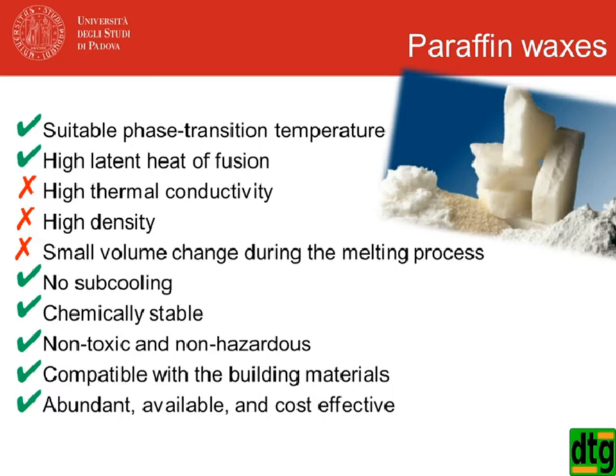High thermal conductivity, of course, this is one of the major limitations of paraffin waxes. Usually a paraffin is likely to show 0.2 watt per meter Kelvin. And so taking this problem will allow us to understand, or if you want, to start from the worst case, and thus test our procedure.